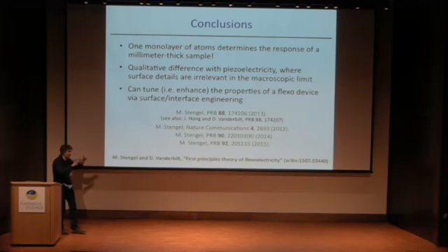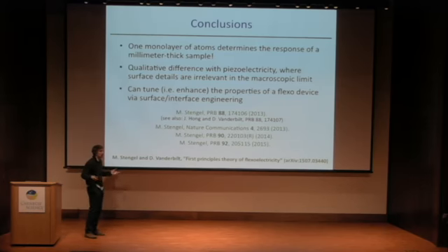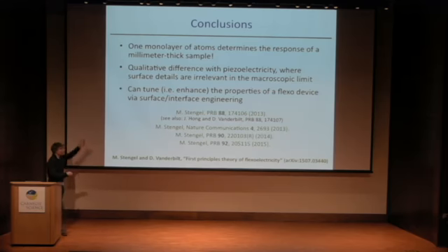If you had everything implemented, then you need a microscopic theory of the polarization response to some perturbation. In principle, once it is implemented, the bulk tensor can be calculated at the bulk level. But then you still have the problem of the surface, which if you want to calculate the total response of a real, finite system, then you need also the surface contributions. And these are surface specific, so you do need a surface calculation. It depends on the termination, it depends on the chemistry at the interface.